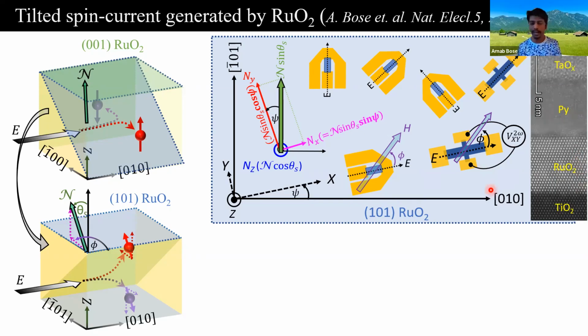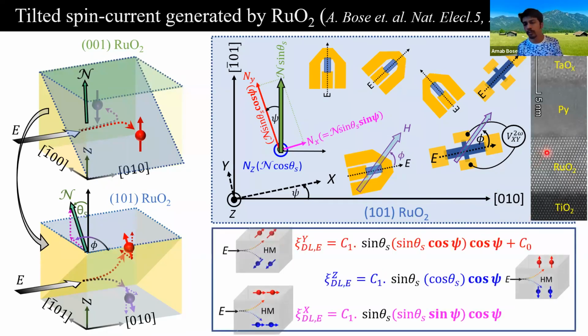Previously, I discussed that this magnet absorbs spin current and it will experience torques. So we will measure different types of spin orbit torques as a function of crystallographic directions. So this magnet will experience spin torques from the y component, z component, and x component spins, as I discussed here. And importantly, they will have a specific angular dependence. For example, the y component of spins will have cos square psi, the z component should have cos psi, and the x component should have sin 2 psi angular dependence. Let me explain a bit the derivation of this.